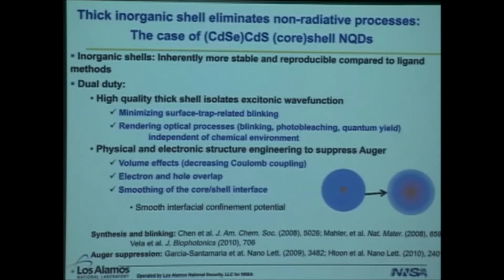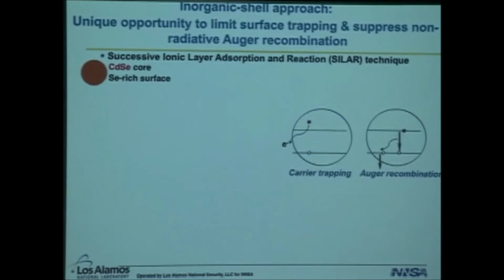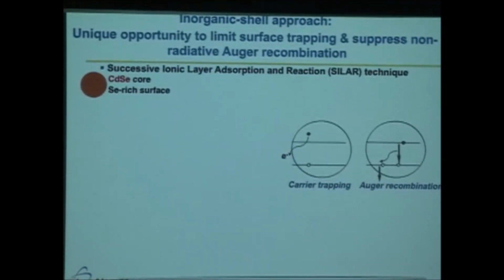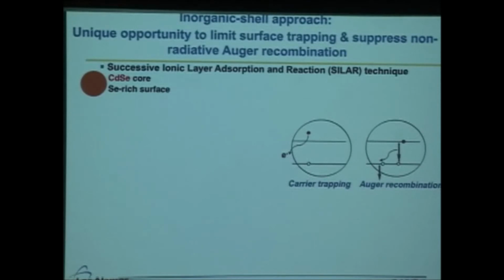We also had a model from the vapor phase community. If you look at epitaxial quantum dots grown by MBE, if those are prepared properly, they can exhibit non-blinking behavior and also suppression of Auger recombination. So effectively what we were attempting to do was to take an epitaxial quantum dot and make it in the flask at low temperature, using simple, cheap methodologies. We had to find a method of growth that would allow us to retain single crystallinity and minimal defects in our quantum dot, even when growing many, many monolayers of shell material.